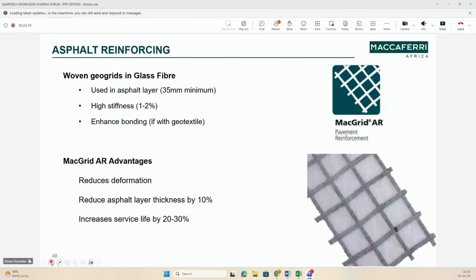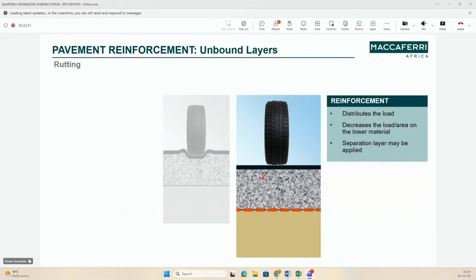So effectively, if you're looking at that load bulb, if it starts here, it's quite narrow. And depending on the quality of the material, that load distribution gets wider if it's stronger. If it's very weak, it will punch straight through here. And that same load gets distributed over a wider area. So that comment about decreasing the load, it's the decreased net load per square area that's been applied on that material. Now, what we can also do by putting in reinforcement is make it spread out further. But what also starts happening is we start looking at separation layers as well to make sure that we don't get the materials mixing.